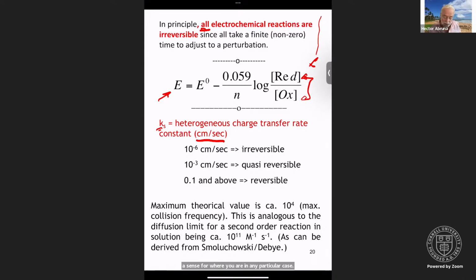If your system has a Ks of less than 10 to the minus 6 centimeters per second, we can consider this as being quote unquote irreversible. If it's above 0.1, we can consider that being reversible. If it's in between, and this gets very gray, somewhere in the neighborhood of 10 to the minus 3, 10 to the minus 4 centimeters per second, we call it quasi-reversible. Meaning it's going to matter a lot in terms of how you actually measure the rate.